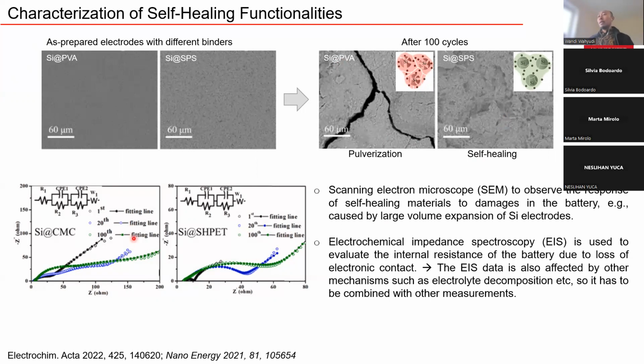Another technique to evaluate the self-healing functionalities is electrochemical impedance spectroscopy, which can tell us about the change in the loss of electronic contact in the cell during cycling of the battery. However, we need to remember that this data is also affected by other mechanisms, such as electrolyte decomposition etc.. So it is important to combine this EIS measurement with other techniques.